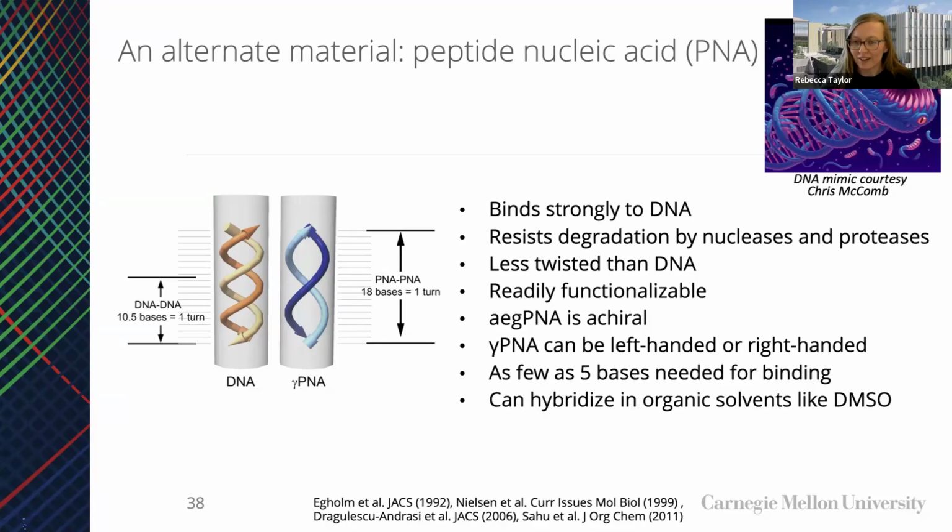It's more conformationally constrained, and so it doesn't actually bind mismatches really well. So you have to get the right sequence. It's better at binding the right sequence. So for an engineer, this is extremely exciting just in terms of its high affinity and its mismatch intolerance. But it also is not recognized by nucleases and proteases. So it's not a substrate for either.